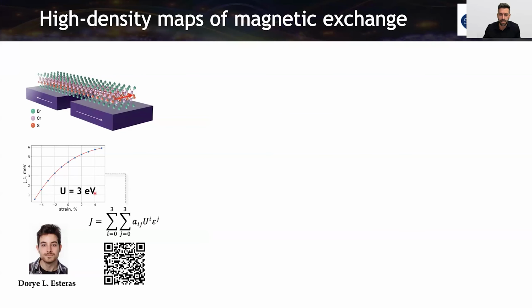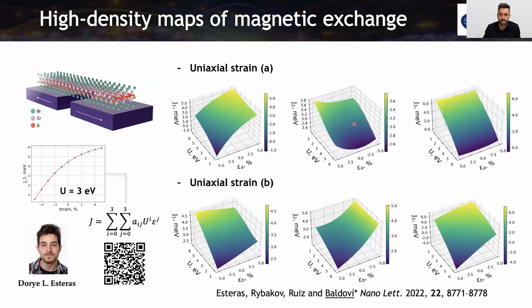And we started computing the effect of strain on each one of the exchange interactions. So we are calculating J1 for different strain levels and also varying the Hubbard-U. We can fit this with the least squares method, and then we can calculate these high density maps of magnetic exchange. This is applying uniaxial strain along the A axis, and this is along the B axis, and we can observe the evolution of J1, J2, and J3.